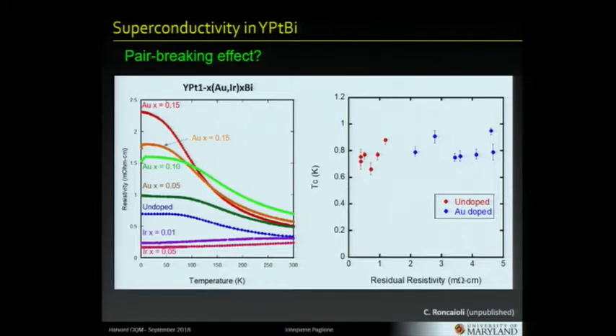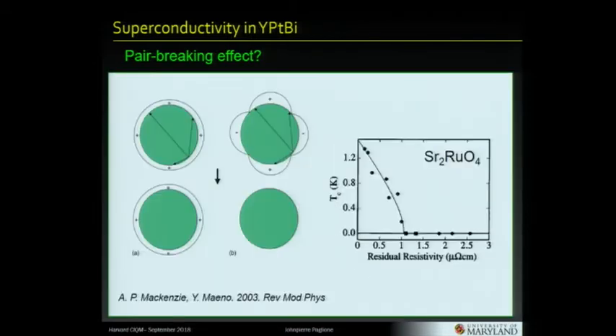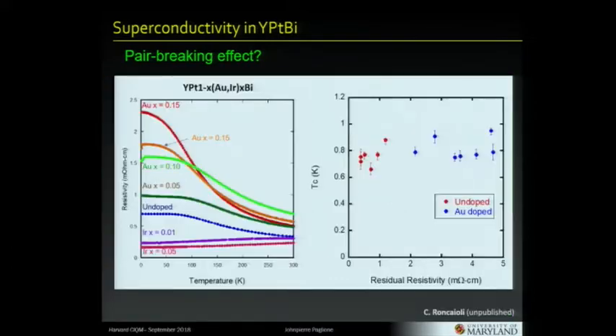This is just transport experiments. This is unusual. It's nothing like this behavior, of course. But we have to keep in mind that this scale here is meaningful, and it's not necessarily a large scale. This could be tiny compared to where you have to get to actually cause some pair breaking. The key parameter is the coherence length, which is extremely short in this system. It's 15 nanometers. And that's really one of the biggest puzzles about the superconductor. How do you have a 15 nanometer coherence length? It's very, very short.